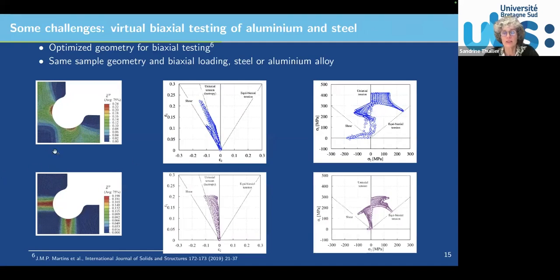One of the challenges is that it will depend on the material. And in this case, it's a purely numerical study. And this is only 1/4 of the sample. So imagine you've got a biaxial loading. You pull along that direction, you pull along this one too. And this is just 1/4 of your sample. In this first line, this is for a steel, and in this second line, this is for an aluminum alloy. So it's purely numerical, but the material parameters were taken from a real material.